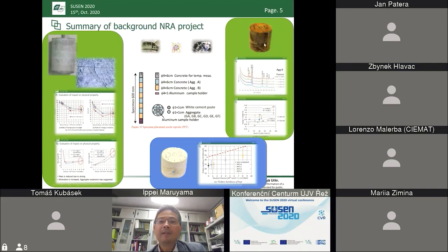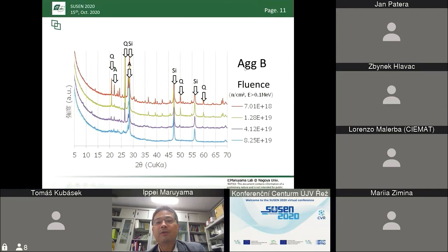So this is the result. This is the result of XRD of one of the irradiated aggregates. We show 4 different levels of neutron fluence, and you see that at very small neutron fluence, we clearly see the peaks of alpha quartz and also albite inside the aggregates. These are the major rock-forming minerals of the aggregate. But after the irradiation, the peaks are reduced. For example, if we look at the peak of the quartz here, we see the reduction of the height like this. And above 8 to 10 times 10 to the 19, it has become almost amorphous. We don't see any peaks.